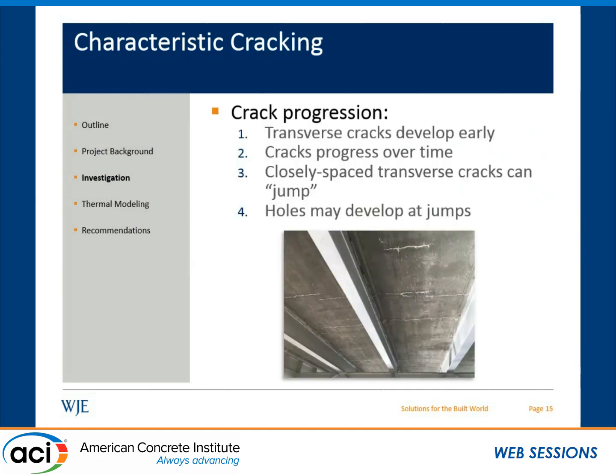So our theory based on our field and laboratory investigations, first is that the transverse cracks develop very early. Our petrographic analysis indicated that the cracks were very early in origin, not only because they were observed by the DOT at 14 days or less, but also because they tended to wind around the aggregates. The cracks progress over time, and so as you see in this figure, they typically originated right around the girders and then progressed outward from there. When they get closely spaced, like shown here on the left, that's where the potential for jump cracks happens, and you can actually see a jump crack forming here on the right. And then if the jump cracks become continuous, that's when the holes can develop.